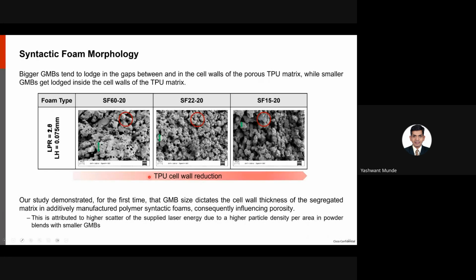That also resulted in a reduction in the cell walls, as is apparent in these SEM images. So we showed for the first time that GMB particles dictate the cell wall size, and this is attributed to higher scatter of the supplied laser energy due to higher particle density per area in the powder blends, with the highest in the smallest GMB particle case.